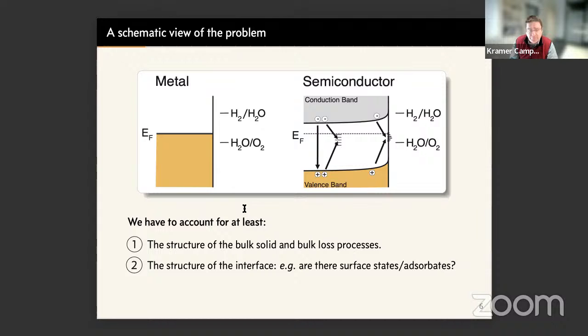So on the one hand, if we're interested in a metal, say in driving water splitting, we have a metal with a large density of states. The sort of top of this density of states is characterized by the Fermi level, right? When you change a bias now in the metal electrode, you can understand what you're doing is changing the Fermi level in the metal. So as you raise this Fermi level up, the energy scale here is the vacuum energy. Eventually, you drive hydrogen evolution, the reduction half reaction here. And if you lower it sufficiently, of course, you will drive the oxidation half reaction, and electrons will flow from liquid water on the right side into the metal.